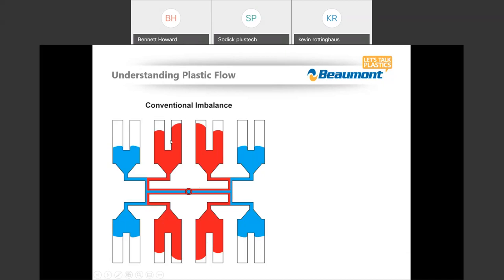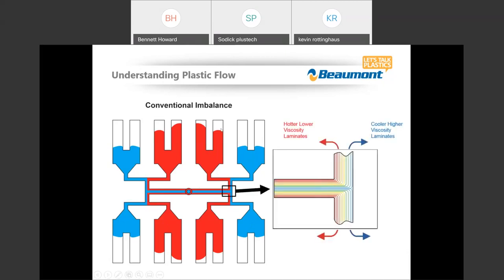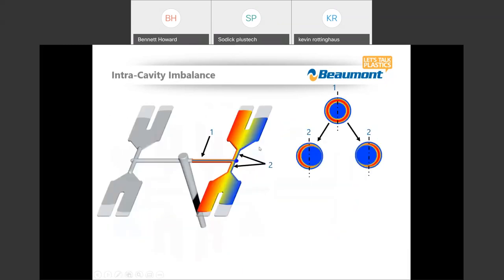We can see how these cavities are receiving the hotter, less viscous material, and the cavities out here are receiving the cooler, more viscous material. You can even look within these parts themselves, and we have variations within them where the highest shear rate develops on one side of the part. Why? Because those are the laminates that were experiencing that shear the longest period. So these laminates on this side of this part right here are actually hotter and less viscous than even these laminates over here. And we call that essentially an intra-cavity imbalance.